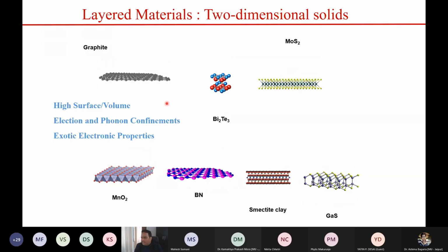And once you exfoliate it, you enter the extreme nanoscale, which is the atomic layer, and you have exciting physics as well as exciting properties of the materials. For example, high surface-to-volume ratio and electron and phonon confinement in these materials give rise to exotic electronic properties. Graphene is a well-known example. Bismuth telluride and bismuth selenide are also very good materials for understanding topological insulators. And there are several materials like MnO2, hexagonal boron nitride, gallium sulfide, and smectite clay, which are useful for energy storage in the form of batteries and so on. But what I'm going to talk about today is monolayer MoS2.